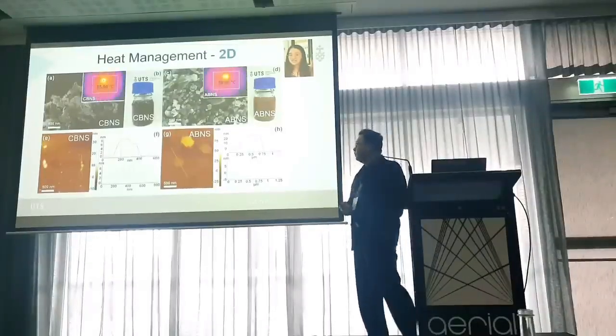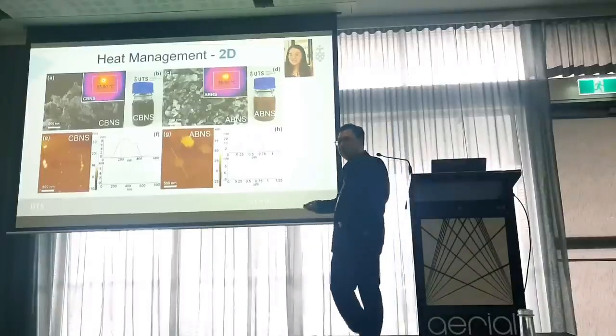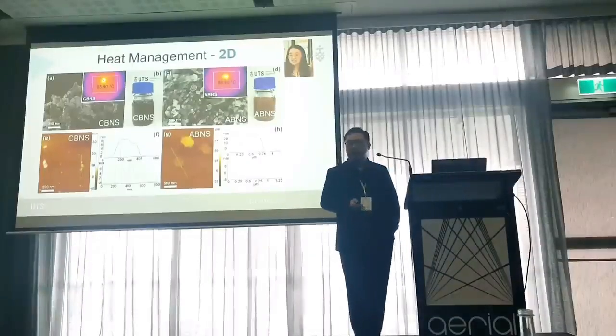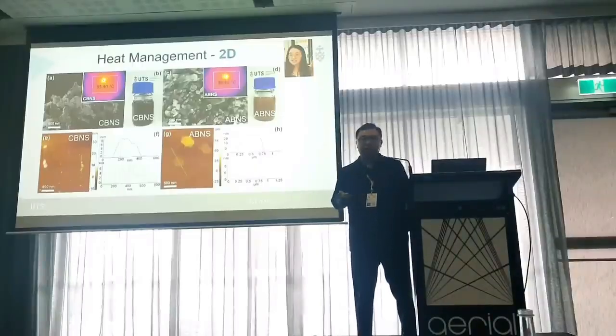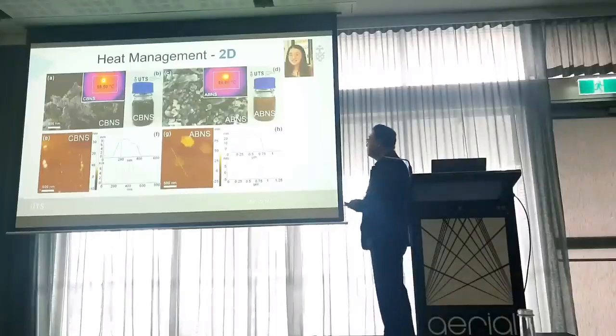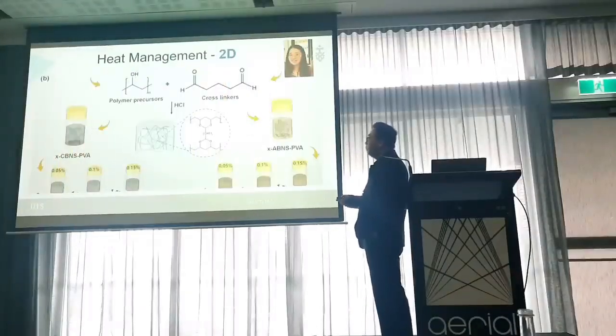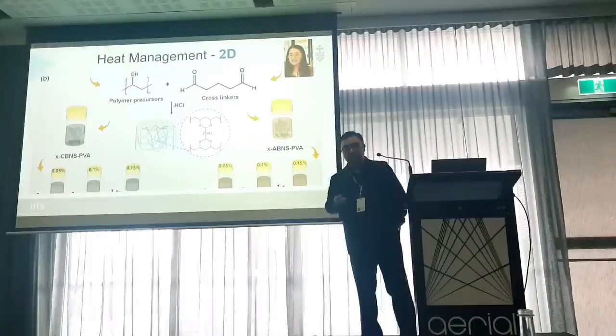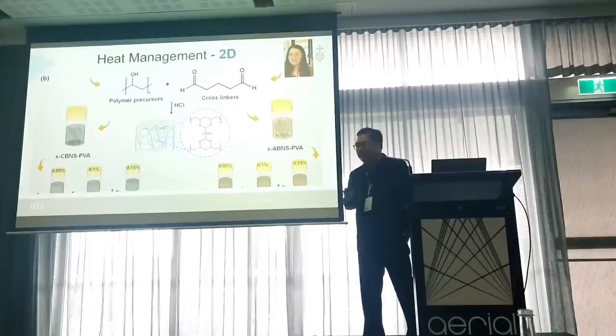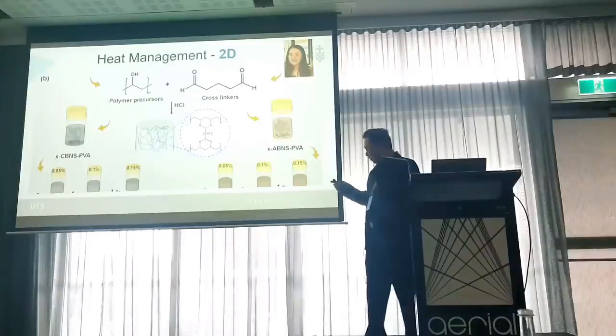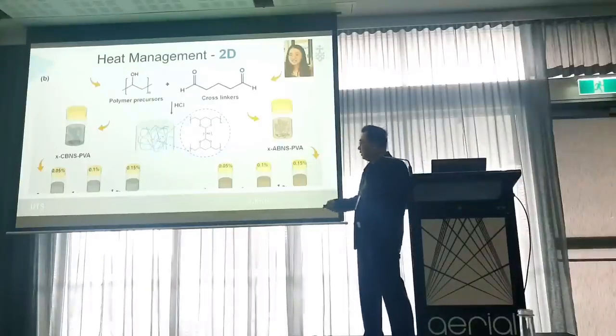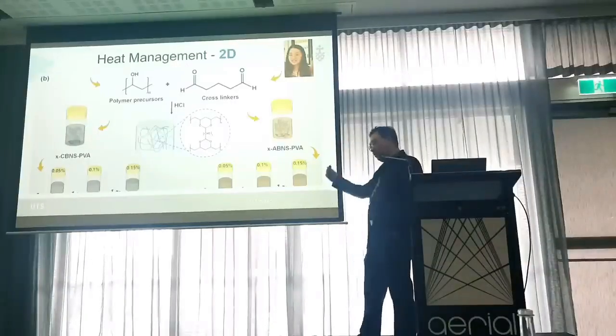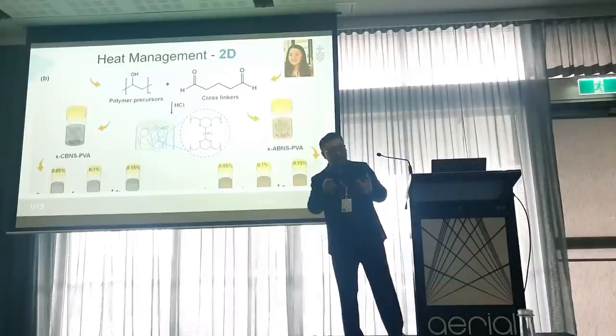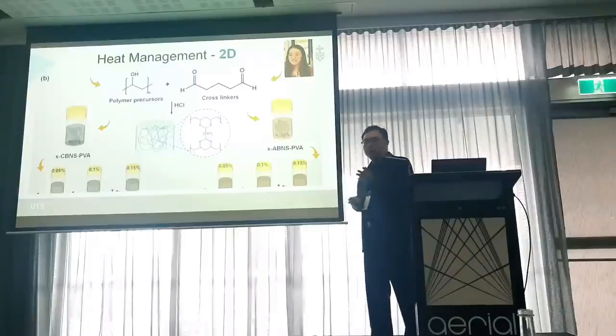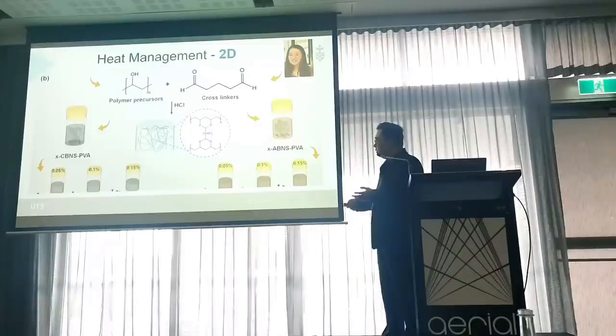We also tested the photothermal performance of these materials. Under the same 10 minutes of solar irradiation, both materials achieve almost the same photothermal performance, reaching about 56 centigrade in 10 minutes. And then we use the same polyvinyl alcohol as a polymer matrix and add a very tiny amount, a trace amount, 0.1% or 0.05% of 2D materials as the photothermal materials into the hydrogels. Through the same cross-linking and freeze-thaw process, we successfully prepared the PVA hydrogels with 2D photothermal materials, with different types of photothermal material.